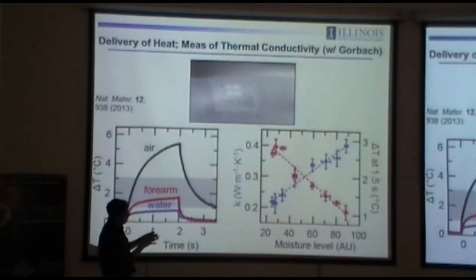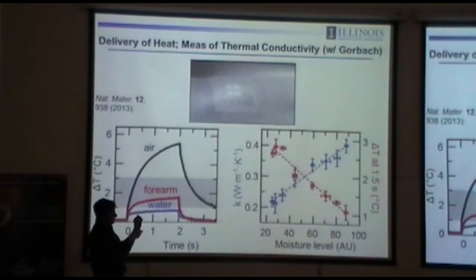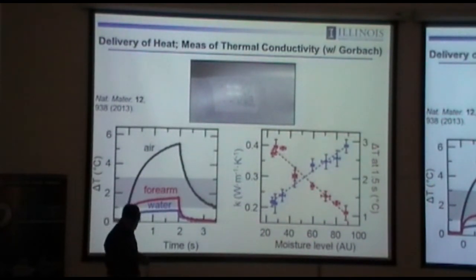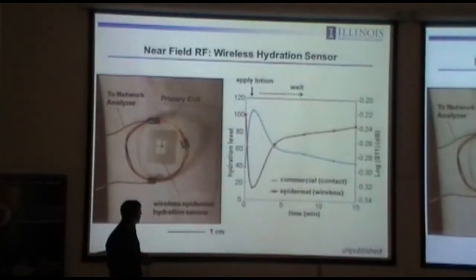You can also do things that aren't even possible at all with the IR camera, because you can use these tiny temperature sensors, they're basically resistive-based temperature sensors, simultaneously as heaters. So you can pulse heat into the skin, and then you can watch how that heat diffuses. And it turns out that measuring the diffusivity of the skin allows you to make conclusions about the skin conductivity, which turn out to correlate very strongly with moisture content. So you can measure hydration level as well at the surface of the skin. And that's another measurement capability you can't do with an IR camera.